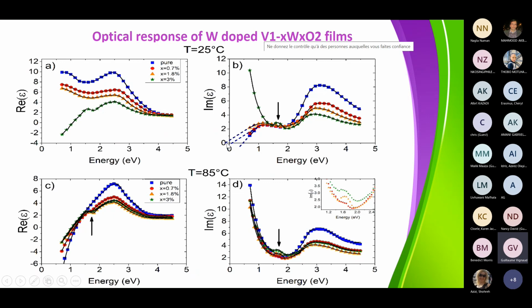So it means that even at 1.7% of doping, at room temperature, you begin to be at a level where you are almost conductive. Okay? You kill the gap. And of course, if you go to 85°, everything is consistent with a metallic structure. You see it very well in the real part of the dielectric function, and also very well in the imaginary part, because of this big tail, the Drude component of the dielectric function.